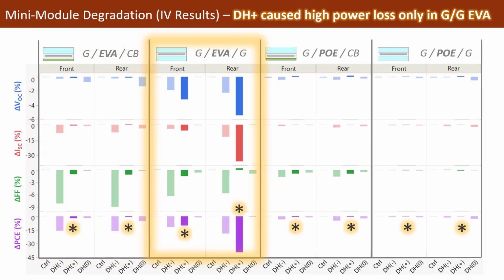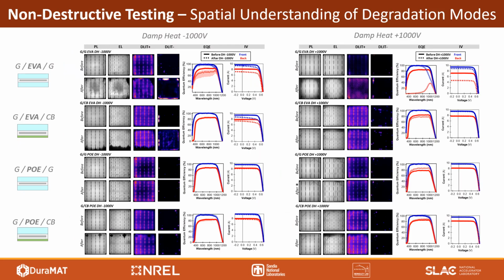The only case where negative bias damp heat did not give the biggest power loss was for the glass-glass EVA module, specifically on the rear side. As you can see here, the glass-glass EVA sample had the greatest power loss under positive bias damp heat, and this was mostly associated with VOC and short circuit current losses with minimal change or even a slight improvement in the fill factor.